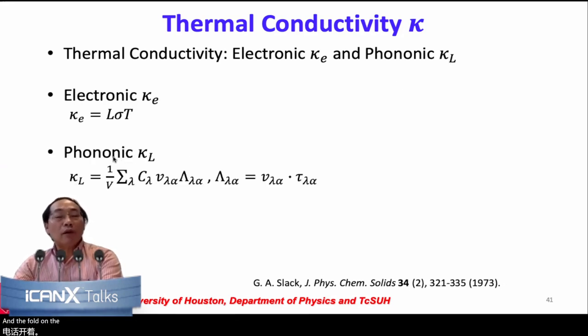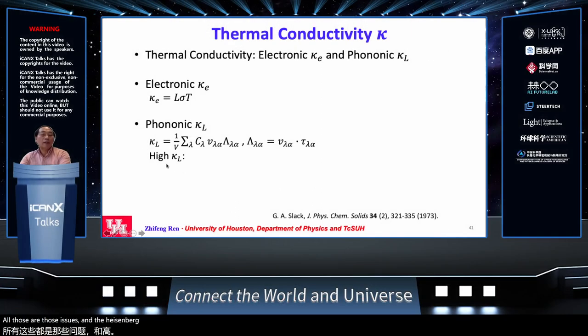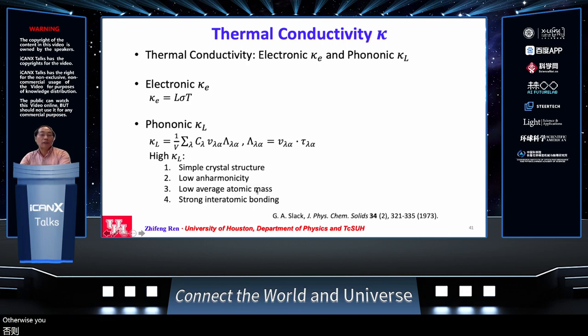The phonon lattice part is very much related to specific heat, group velocity, and also the mean free path of the phonons. And the mean free path, of course, is related to the time, frequency, all those issues. And for high lattice thermal conductivity, traditionally by Slack's rule, you have to have materials with very simple structures, no anharmonicity, and also very low atomic mass. Otherwise, you don't get high thermal conductivity. Of course, the crystal structure has to be cubic, very simple, with very strong bonding between the atoms. But no one was able to demonstrate other materials with high thermal conductivity.